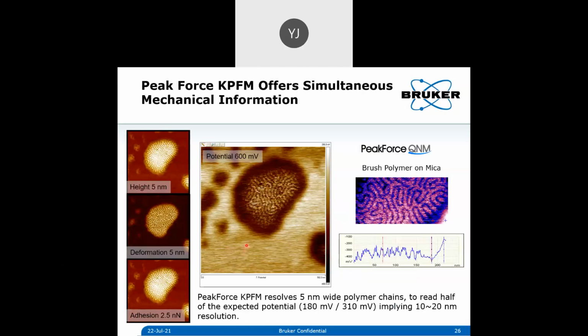So again, now we can just show the strength. You can see here we have the height, the deformation, adhesion, and the KPFM data together of the very complex brush polymer on mica. So this just shows strength. So like, for example, if you have some contamination, sometimes it might be very difficult to catch it with the potential data alone, but now you have multi dimensional data on your sample, you can clearly identify what is causing what kind of signal, right?